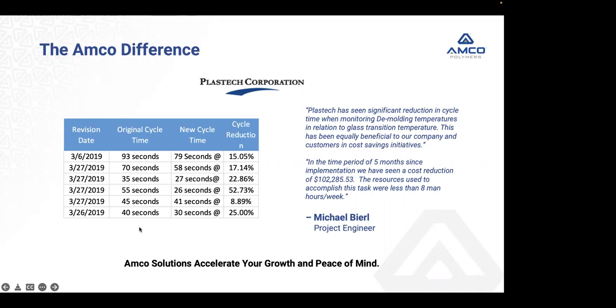Here they did, this was back in 2019. I just haven't asked them to update this because this is just great information. But the original cycle time was 93 seconds. The new cycle time was 79 seconds. They saved 15% cycle time. Here on this one, 55 seconds to 26 seconds. Now, all these actually went through quality. They tested them. They verified that the dimensions never changed. And all the cycle time savings were theirs to keep or to share with the customer.